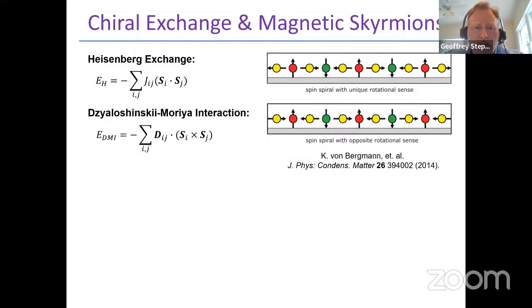So in most magnetic materials, the spin configurations are either parallel or anti-parallel because of a Heisenberg exchange interaction that prefers collinear alignment of spins, that gives us ferromagnets and anti-ferromagnets. In some materials with a broken inversion symmetry and strong enough spin orbit coupling, there's a chiral interaction known as the Dzyaloshinskii-Moriya interaction, and that prefers spins to align orthogonal with one another as opposed to collinear. And it prefers to have a particular chirality, so a left-handed versus a right-handed chirality, one of those would have a lower energy than the other.